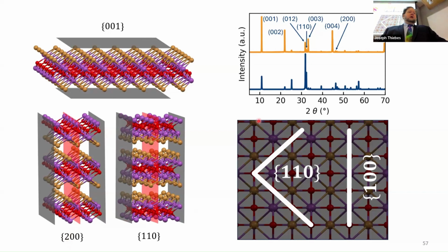And so also Paul did this XRD, which shows really intense peaks for the 001, 002, which is the large flat faces, 003, 004. Those are all the large flat faces. There is one peak that is super visible here that is the 110. It's pretty small. I think there's another one over here that's too small to show up on this graph at this size, but those are the lateral sides. And the reason that there's such small peaks, we surmise, is that the way that they're deposited on the glass for the XRD, those surfaces are vertical, which is not going to produce very much reflection of the X-ray. So we're not seeing very big peaks there. Also, they're a lot smaller surface area. So both of those factors are going to lead to small peaks.